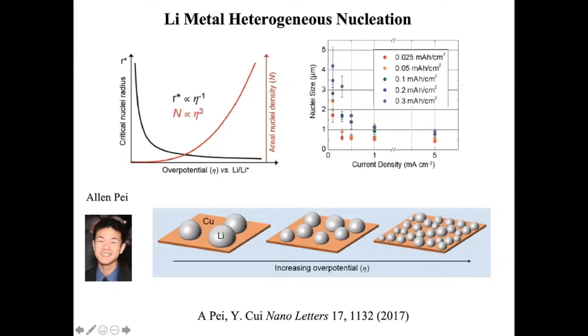If you increase the overpotential, as drawn right here, for nucleation, classical nucleation theory will tell you if you increase the overpotential, you drive it harder, you have smaller nuclei, but the number density is increased a lot. The scaling law is shown on the top left: the critical nucleus radius will go down with overpotential. The relationship is 1 over overpotential. And the number density will go up as a cubic function of overpotential. So we actually measured that. Top right is the nuclei size versus the current density. The higher the current density, the higher the overpotential. When you plot that, it fits the classical heterogeneous nucleation very nicely.